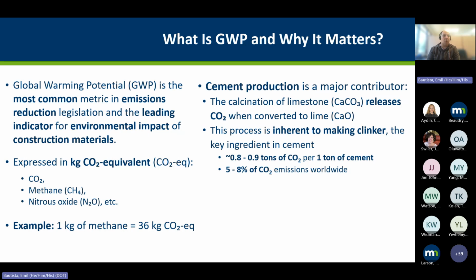Actually, what makes us also large is the amount that we use. We use quite a bit of material to do our infrastructure, so that's another important point. And when we look at cement, for every ton of cement that we produce, we were emitting around 0.8 to 0.9 tons of CO2. And cement production is, I've seen, somewhere between 5 to 8% of the CO2